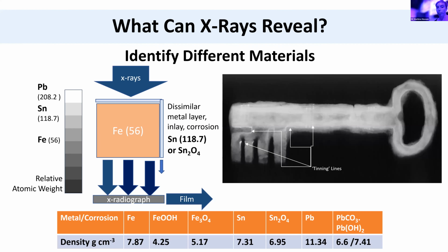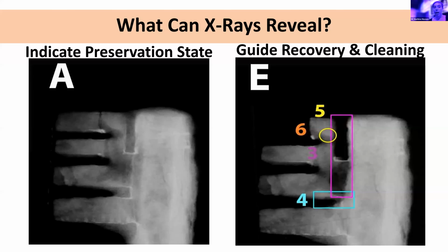And this is experienced as a grayscale event, as I've mentioned. And this in turn can help us predict preservation states. So it can give us an idea of what might be solid versus what might be corrosion product, versus what might be missing. So for an example, these very, very dense white lines that are very well exposed, this is most likely our tinned material here in these little nooks and crevices. In comparison, this much less dense material is probably corrosion product, since it's a lot less white, it's a lot more exposed.